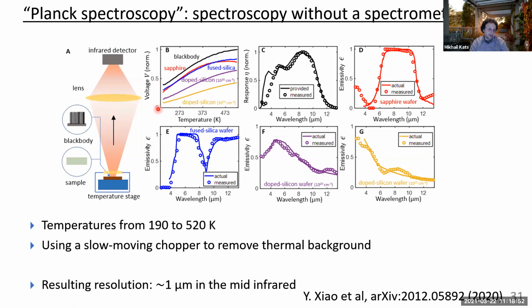So this is the voltage on the detector versus the temperature for a bunch of different samples. So we have the black body sample, and then we have a bunch of test samples that we wanted to use to do these measurements. So we again used our polished fused silica sample. We used a sapphire sample. We used a doped silicon wafer with a phosphorus doping at a level of 10 to the 20 inverse cubic centimeters. And then we used a different silicon wafer with phosphorus doping of 10 to the 21 inverse cubic centimeters.